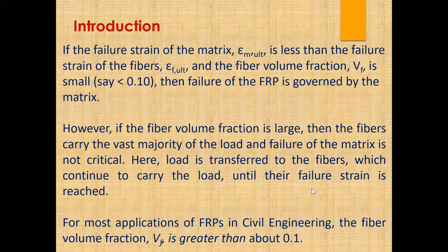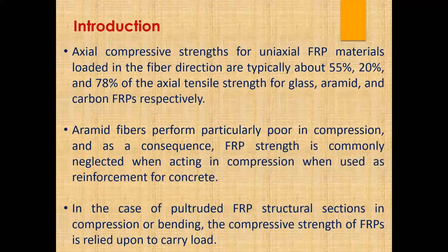And for carbon FRPs respectively. So in that particular case, for the aramid the compressive strength is very low, and for carbon it is very high. Aramid fibers perform particularly poorly in compression, and as a consequence, FRP strength is commonly neglected when acting in compression when used as a reinforcement in concrete. So in the case of pultruded FRP structural sections in compression or bending, the compressive strength of FRPs is relied upon to carry the load.